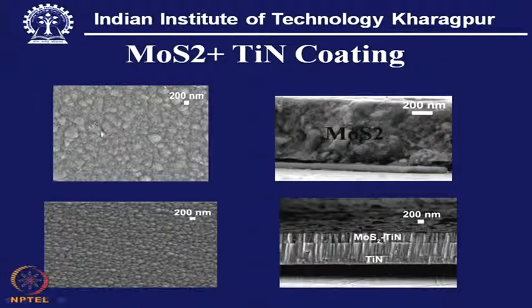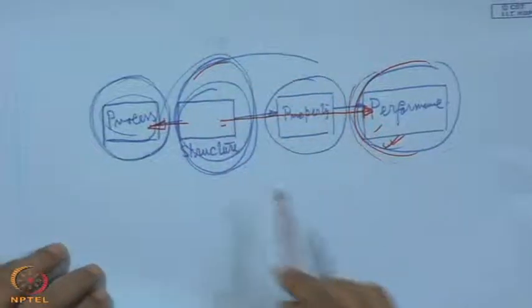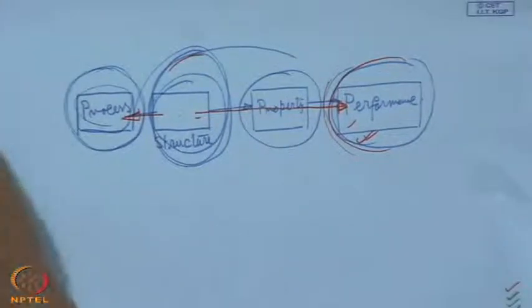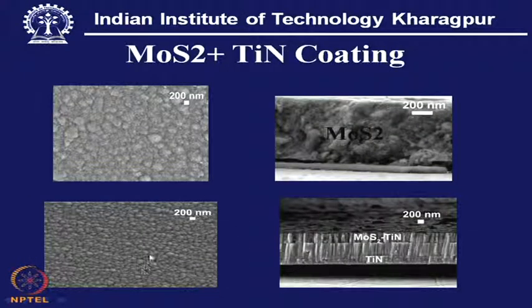Here we see a porous, spongy structure, which is not so densified. However, when titanium nitride and MoS2 are combined in right proportion, we see grain refinement and densification of the coating, and obviously one would expect this coating to be better than this one from the cutting point of view. This physical characterization of the architecture gives us a clear indication that this coating holds some promise.